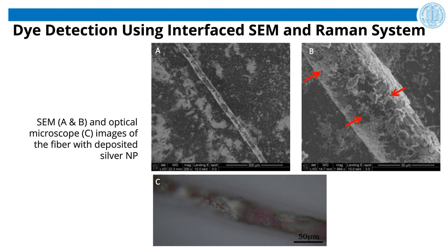On this slide, we can see the alpaca fiber fragment with deposited silver nanoparticles. Silver nanoparticles were deposited from colloidal solution. And it is obvious that nanoparticle distribution is not uniform on the fiber. That can explain why it is hard to expect good consistency with SERS measurements when they are performed on the optical platform. Image C is an optical image, and it is hard to see where you get a good layer of nanoparticles. SEM allows selecting areas on the fiber where silver nanoparticles form a nice and uniform layer. Then SERS analysis can be directly carried out without necessity of moving the sample.